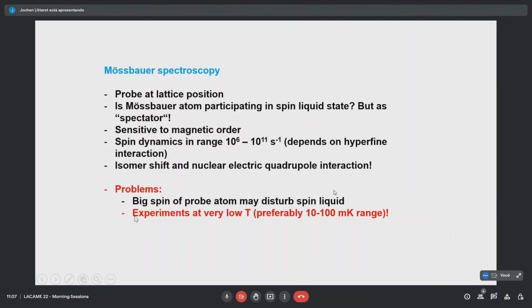Now, the Mössbauer side, I need not tell you, you know best. We are probing at the lattice position. Now, the question is, is the Mössbauer atom participating in the spin liquid? Hardly, since usually Mössbauer atoms have a relatively large spin. Iron, for instance, 3/2, 5/2, or seldom 1/2, in the low spin conditions, but in very rare cases only. But you may use it as a spectator in looking at the surrounding.